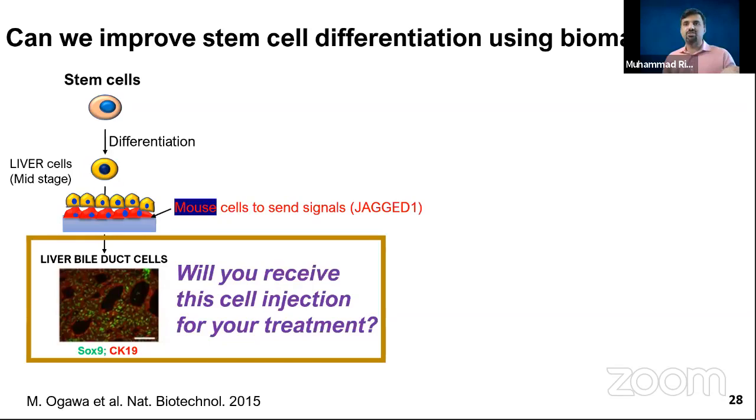One of the challenges in the stem cell field, if I give you a big picture, is that for the differentiation, we use animal-derived products. One thing is called Matrigel. It's a hydrogel which comes from a mouse tumor, basically. The use of Matrigel limits the translational potential because it's a big challenge; in Matrigel, it's difficult to characterize all the components. So basically we want to make sure that the system we are developing is a synthetic system, or at least we know what's in there. Otherwise, it may take years and years of characterization, and we may still not be able to fully satisfy the agencies or regulatory requirements.